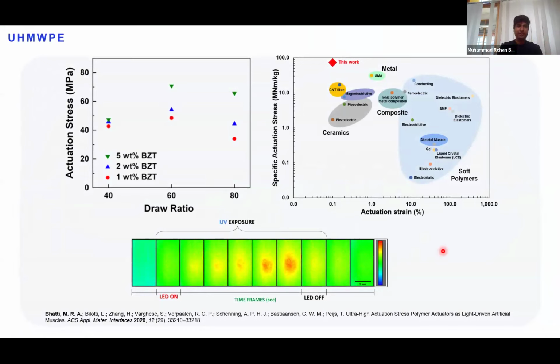just aiming to get high actuation stress because of the higher Young's modulus, and the results were quite promising. We were successfully able to get a very high actuation stress, around 70 megapascal, and this was the highest ever reported actuation stress at the time of our research, compared to other organic and inorganic materials, because of the low density and high Young's modulus of the polyethylene. And the effect was, again, rapid and responsive, and this is all because of the heat generated within the polymer substrate because of the BZT within there.